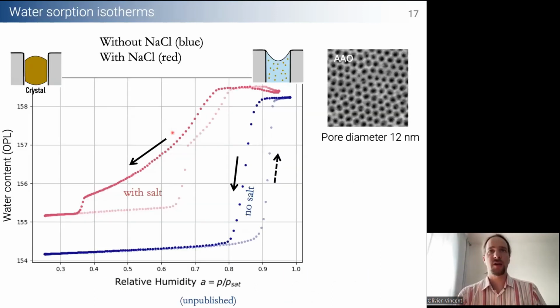And of course, to dry these nanoporous systems, we need to impose very low relative humidities, again, because of the very small pore size. And what we did to just evaluate what happens in these systems with the complete range of relative humidities, but within the nanopores themselves, is water absorption isotherms, which is just a measure of the water content in the system at different relative humidities.